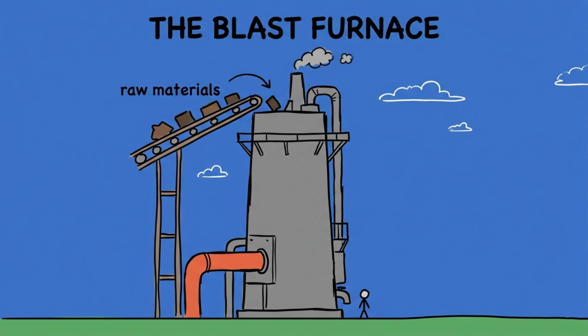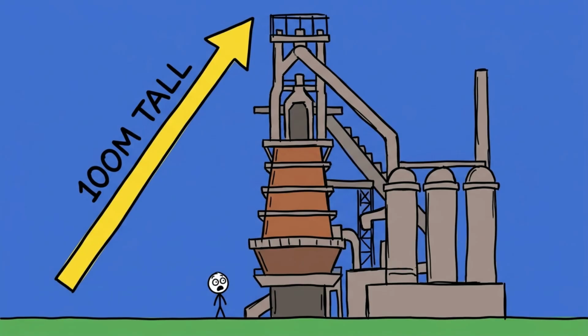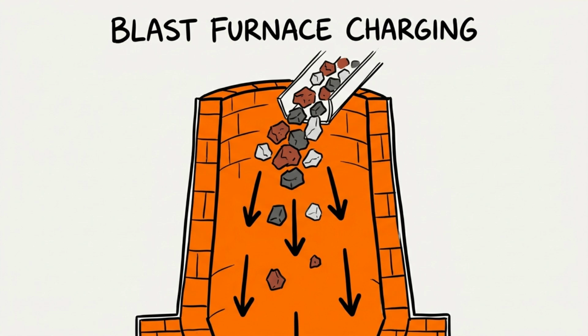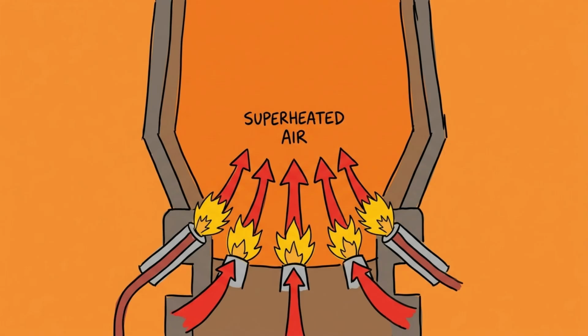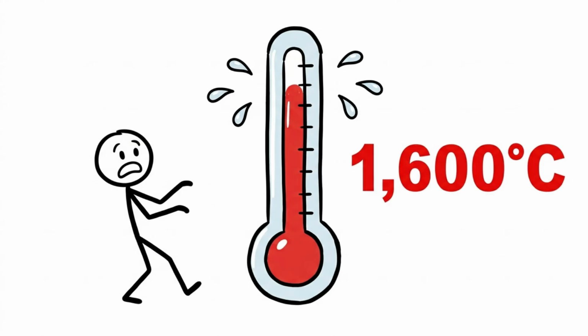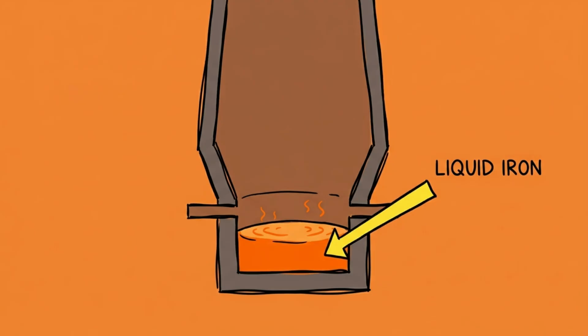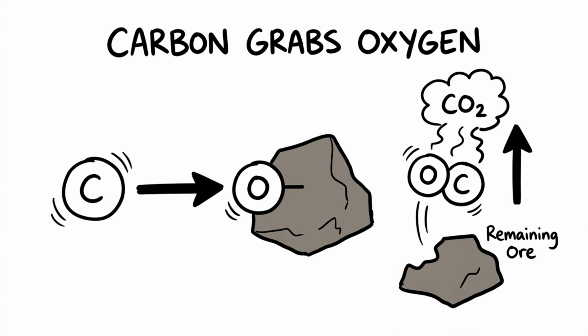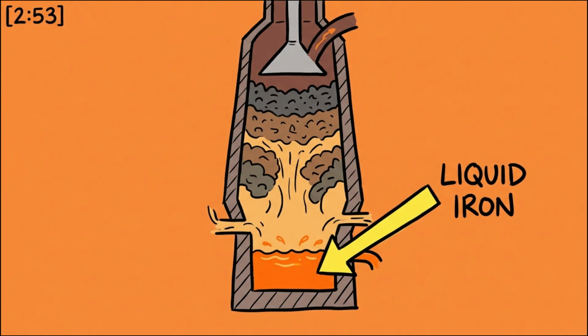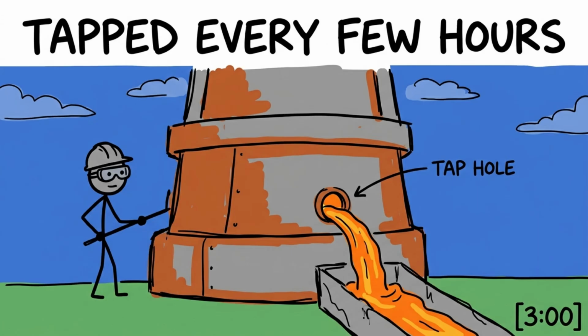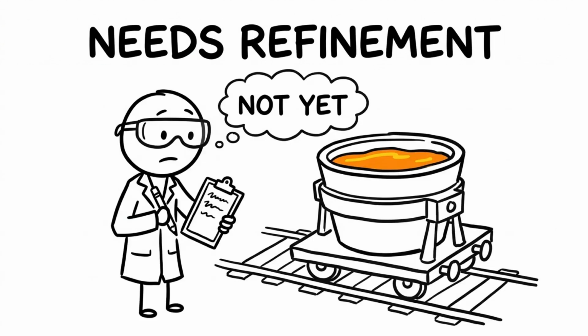Now comes the blast furnace, and this is where things get extraordinary. Some blast furnaces stand over 100 meters tall. Inside, the ore, coke, and limestone get loaded in from the top. Superheated air, over 1,000 degrees Celsius, blasts in from the bottom. The coke burns. The temperature climbs to around 1,600 degrees, hot enough to melt iron. The carbon in the coke bonds with the oxygen in the ore, pulling oxygen away and releasing it as gas. What is left is liquid iron that pools at the bottom of the furnace like a glowing orange river. Every few hours, the furnace is tapped. Molten iron pours out, blazing, sputtering, into enormous ladle cars waiting below.